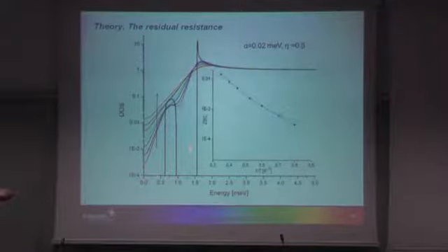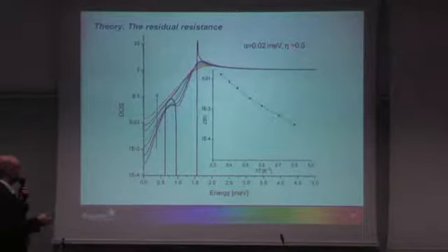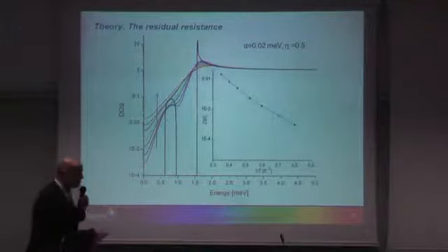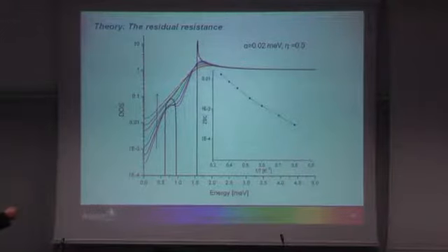But what are eta and alpha? So how does this affect things? In the Shiba theory, this is what would be a perfect superconductor without any magnetic impurities: 0, 0, sharp quasi-particle peaks, merging back into the normal state at higher energies. In the Shiba theory, you have localized states that start to appear inside the gap at an energy given by eta. Alpha is basically the concentration of magnetic impurities. When you increase alpha, you increase the concentration for a fixed eta. This has the effect of broadening these peaks and lowering them too.